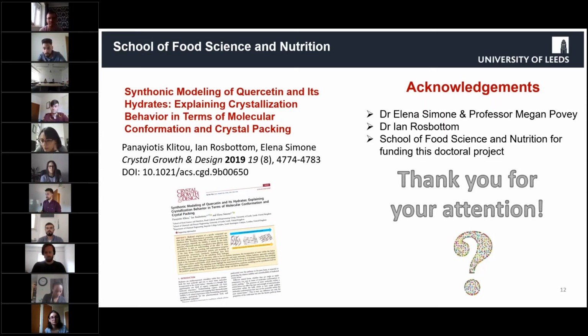And the final question is, so we did do the dissolution of the dihydrate and the DMSO solvate. They are asking if the powder pattern matched the anhydrous crystal structure. Okay, that's a good question, and I should have mentioned that in the presentation. It was found that the anhydrous, the pure form of quercetin, starting from both the dihydrate form and the QDMSO form, did not match the quercetin anhydrous pattern of the quercetin anhydrous structure that we have modeled.